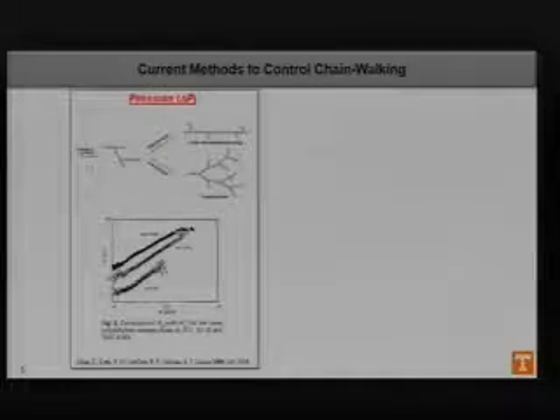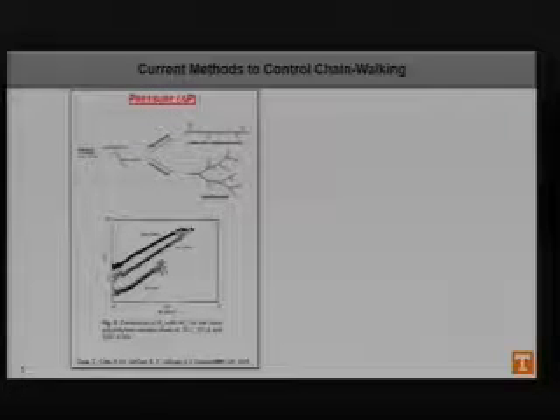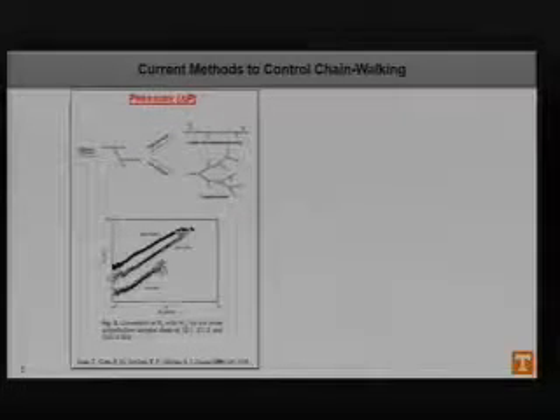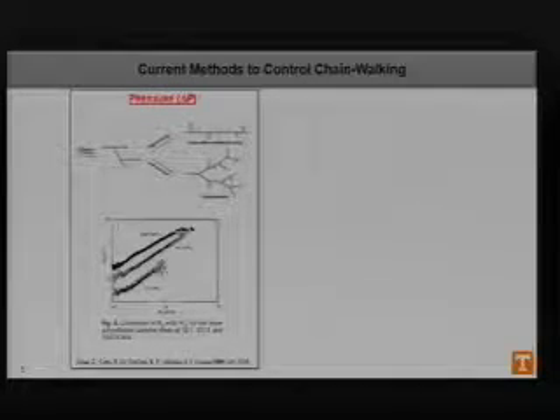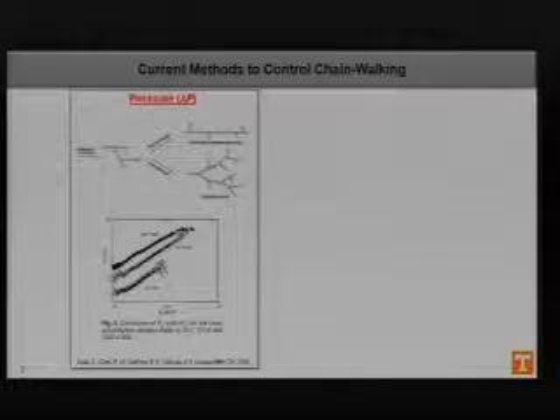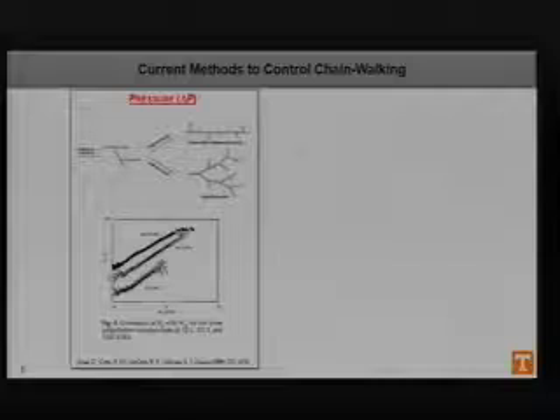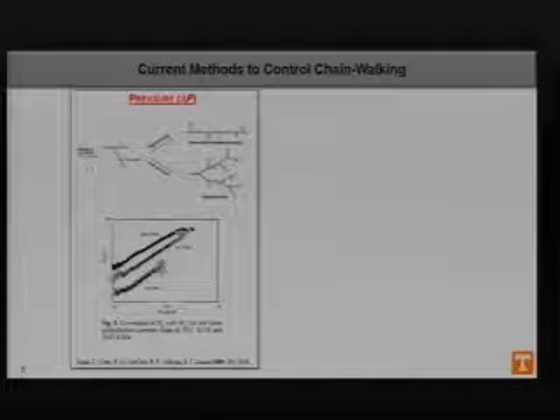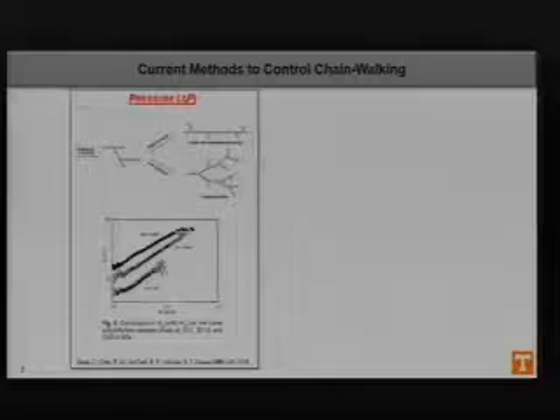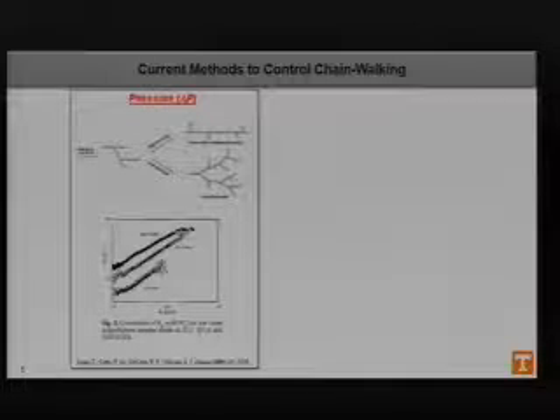Now, there are currently only really 2 methods that are used to control this chain walking mechanism, and the first of them is pressure. If you take a look at the example I have here, as you increase the pressure, you tend to get a more linear structure, which is the harder, more rigid material. And as you decrease the pressure of ethylene, you get a more hyperbranched structure. Now, the Mark-Houwink plot, which is something that we use to represent this, essentially just shows us that the line towards the top left here represents the more linear structure. And as it moves towards the bottom right, we're getting a more branched structure. That's essentially what this means for our purposes.